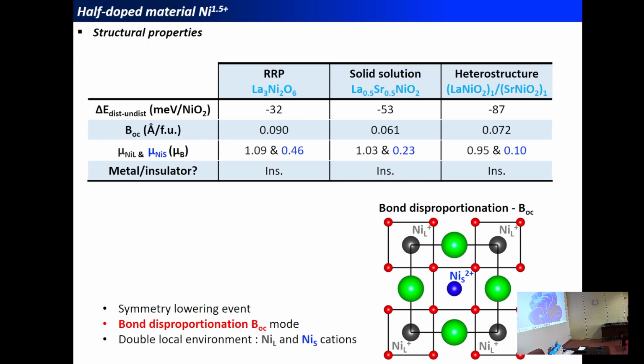Any other question? You were mentioning that it's hard to define the spheres to integrate the charge around. Did you try atoms in molecules or the electron localization function to do that? No, the electron localization function we didn't try. We tried the Bader charge analysis, which is another one. And in this case, effectively, this one has more electrons than this one. But you don't have finally one with one more electron than the other one. You see that there is a difference, but it's not 1 and 0 exactly.